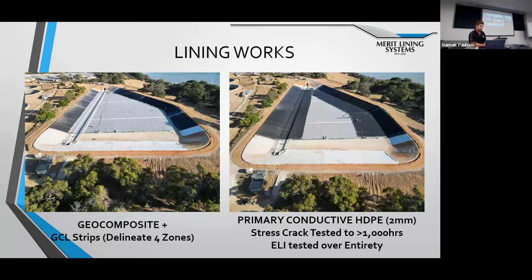The next layer we had was geocomposite as well as GCL strips, which delineated 4 leak zones. I don't know if you can quite see them there, but you've got one that runs up the low flow channel and then 2 across the pond there. This allowed us, or this allows the client, if ever there's a leak, to identify what zone the leak is coming from. On the right is the primary conductive, which went over the top, and this liner was again stress crack tested to over 1,000 hours. It was a 2mm product and conductive, which allowed us to ELI test the final layer as well.